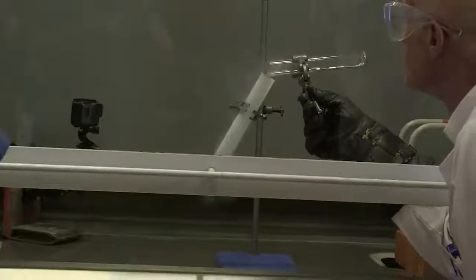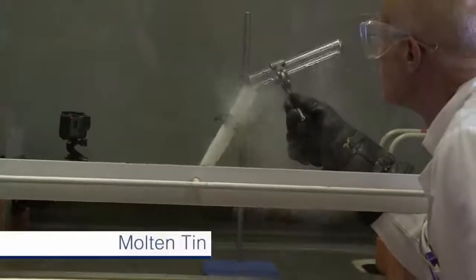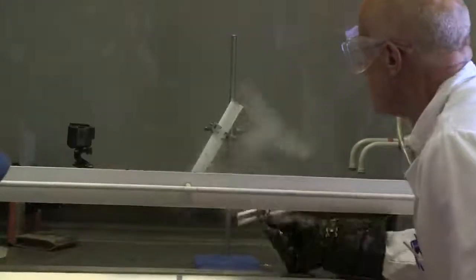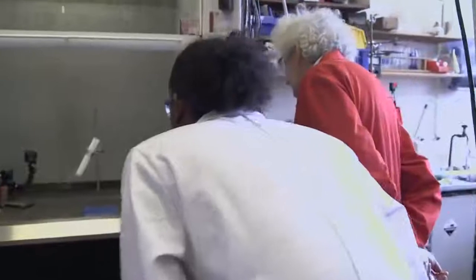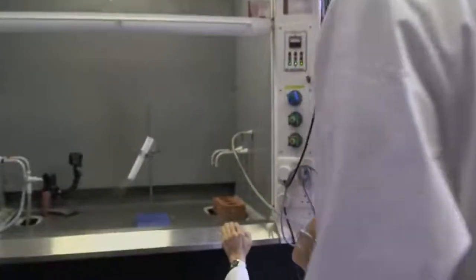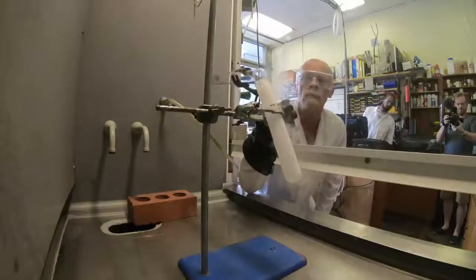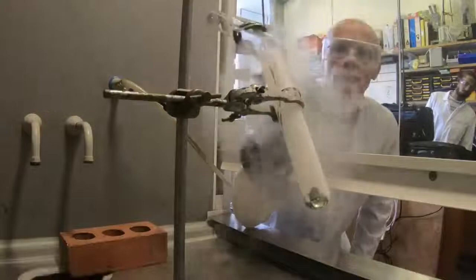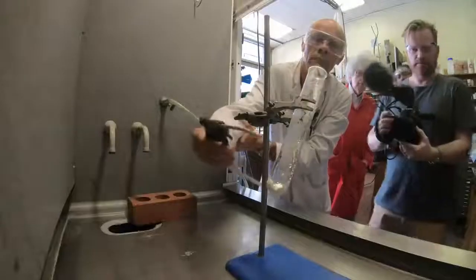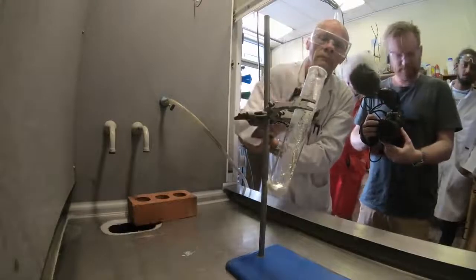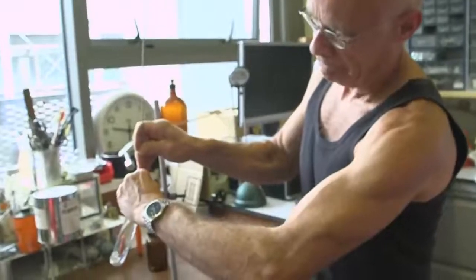So we then tried a different experiment, melting the tin and pouring the molten tin, the liquid tin, into liquid nitrogen. The thinking here was that if we froze the liquid quickly, it would go into the unstable form directly without going through the metallic one. So it was really quite spectacular. When it went in, there were great plumes of vapor, water vapor, as the nitrogen evaporated. And when we took it out, it was a rather beautiful shape of long piece of tin.